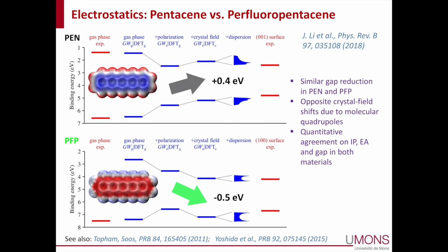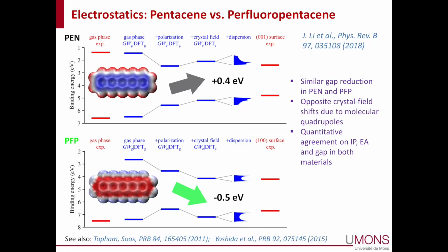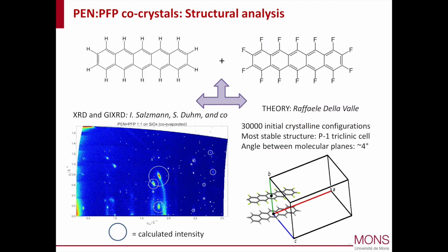So the opposite change in the energy levels due to the charge-quadrupole interaction simply reflects the fact that in those molecules the quadrupole moment is reversed because of the strong CF fluorination effects, withdrawing groups compared to the CH groups in the pentacene molecule. And you can push this a little bit further by looking at a co-crystal of the molecules made of pentacene and perfluoropentacene, and you can make those co-crystals in a one-to-one composition, and they adopt this nice alternated structure with pentacene and perfluoropentacene in a sandwich-like configuration.